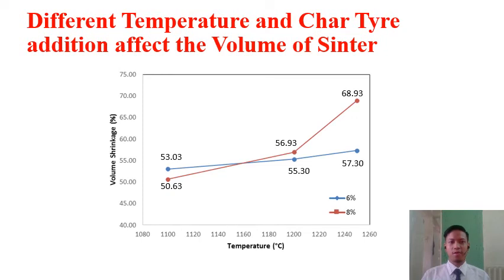This is the effect of temperature and char tyre addition on the volume of the sinter. As you can see, the volume shrinkage for the 6% is 53% at 1100 degrees, and slightly increased to 55.30%, and lastly 57.30%. However, at 8% composition, at 1100 degrees Celsius, the volume shrinkage is 50.63%, followed by a slight increment to 56.93%, and a significant increase to 68.93%. This shows that higher firing temperature, or higher sintering temperature, and char tyre composition reduce the volume of the sinter product due to the densification of the sinter.